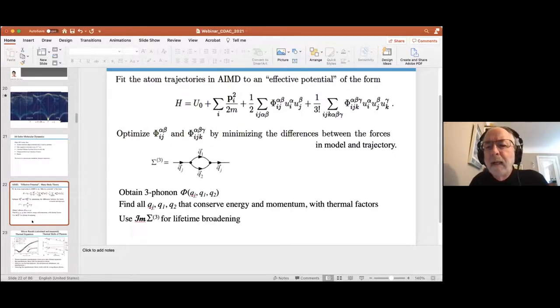When we look at a couple of points in those phonon spectra at a high symmetry point, 111, on L, we see that these frequencies with temperature decrease for the low transverse acoustic modes. The quasi-harmonic theory predicts they have a negative Grüneisen parameter and increases. And that's true. Under pressure, that'll be true. Harmonic theory would show nothing.